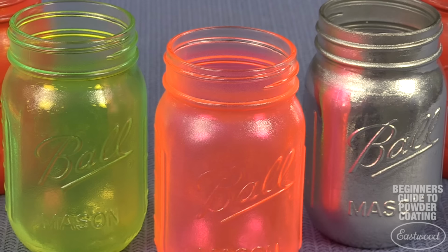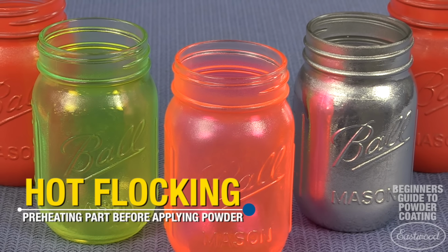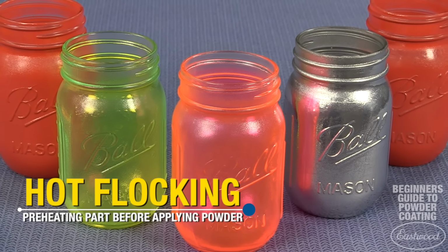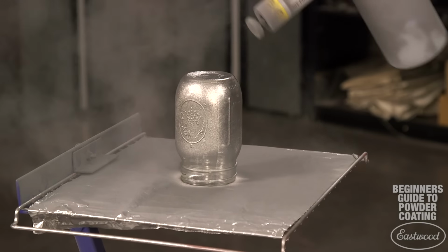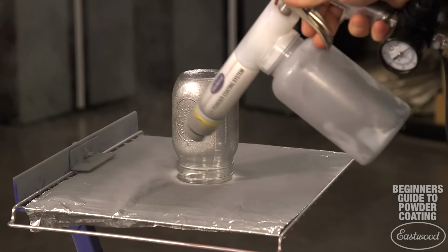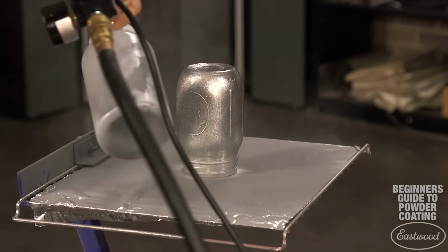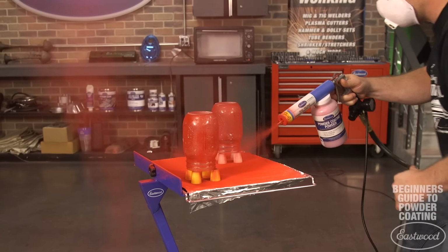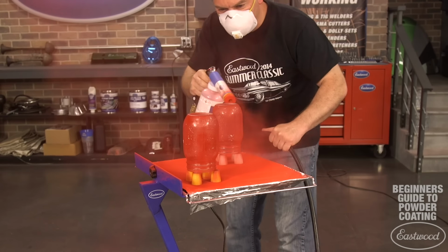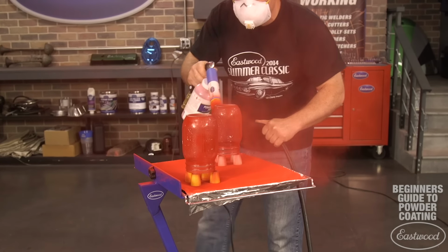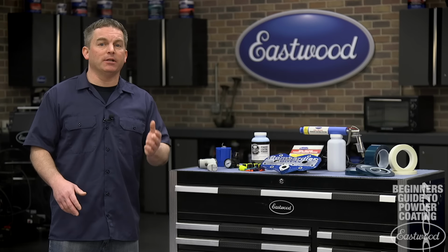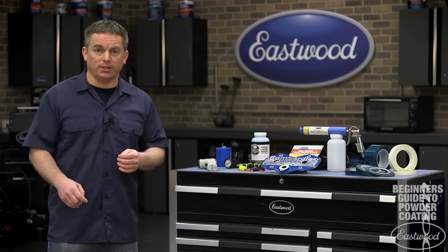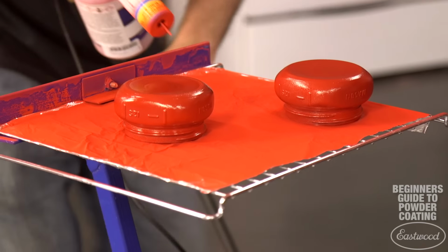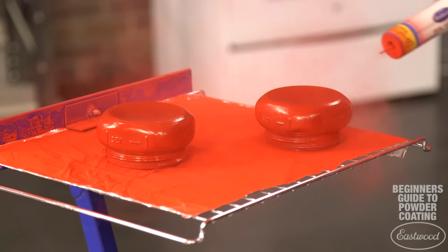You can even powder coat glass using a process called hot flocking, which means the part is preheated before applying the powder. This is done because the glass won't conduct a charge, so it also won't attract the powder. When the part is removed from the oven, the powder is applied quickly before the part cools, and that's because it's sticking to the part because it's hot, not because it's attracted due to the static electricity. You can actually see the powder begin to flow out because the glass is so hot.